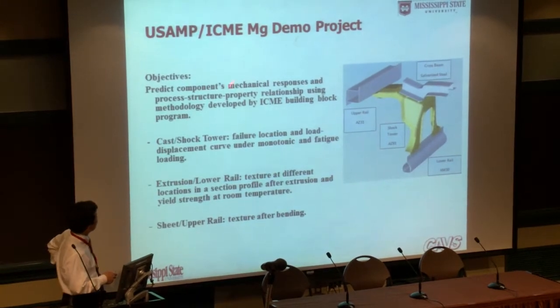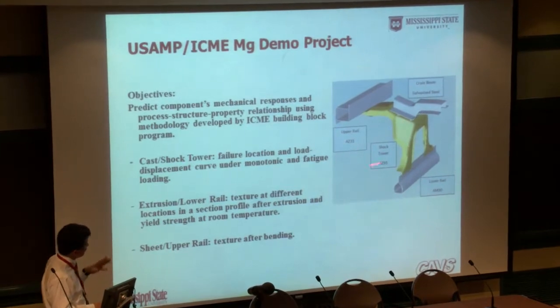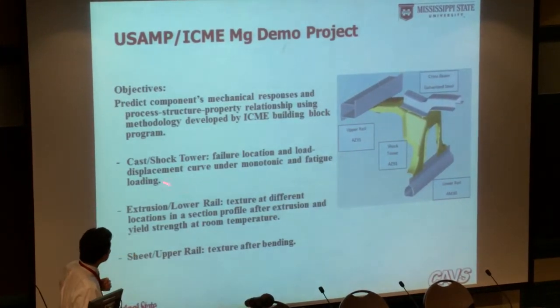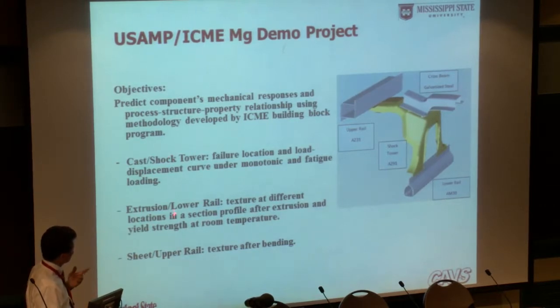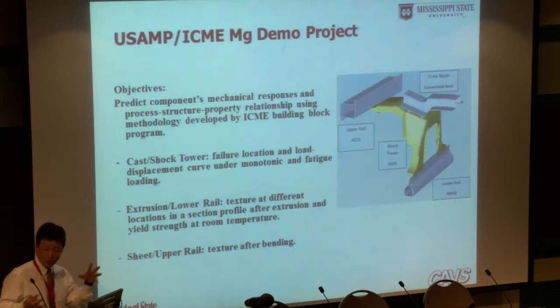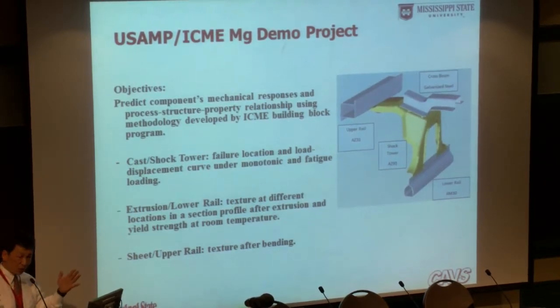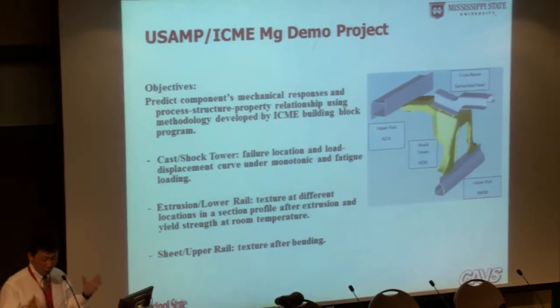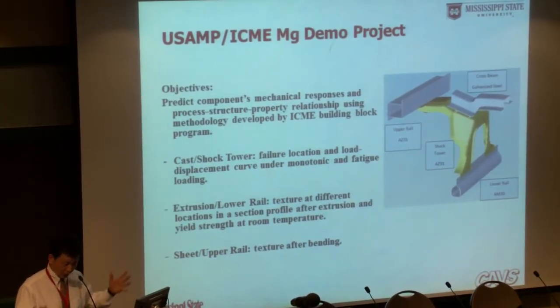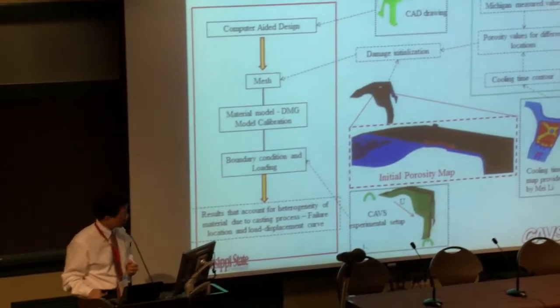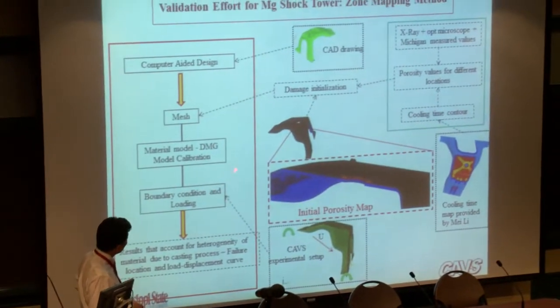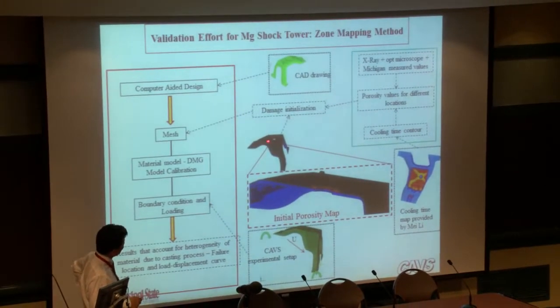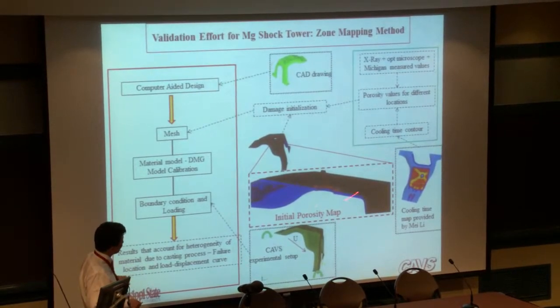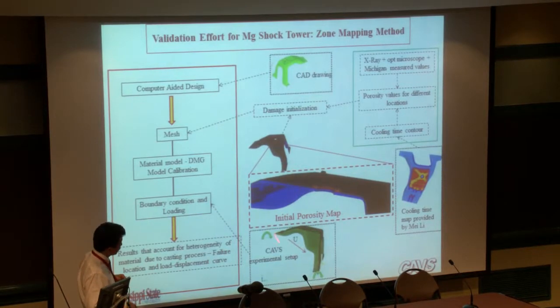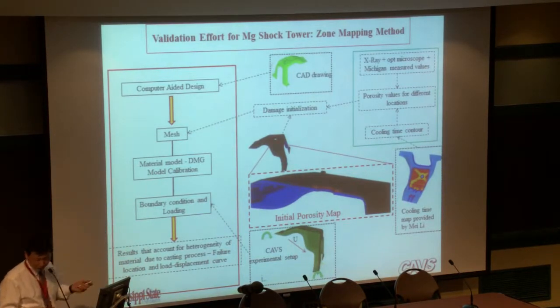So for example, this magnesium front-end project, so we want to predict the mechanical responses at certain conditions. So here has a cast shock tower, like the extrusion lower rails, and has sheet rails, and all this combined together. So basically, you're going to ask your question, can we predict each component, what's the mechanical response based on the processing histories? And then can we put this together with joint, and how that response is under the monotonic and under fatigue loading. So this is the one we finished phase 1 with USAMP. Basically, we use the cooling rate, indicate porosity, which will be heterogeneity distributed over the different parts. And then we look at the certain boundary condition and see how that response is in the laboratory.